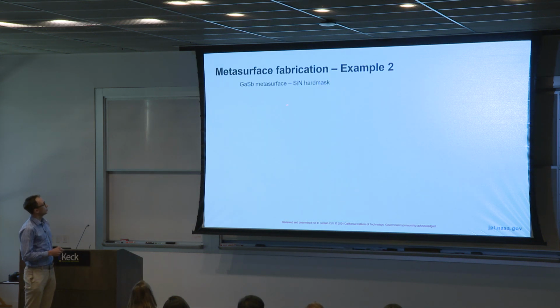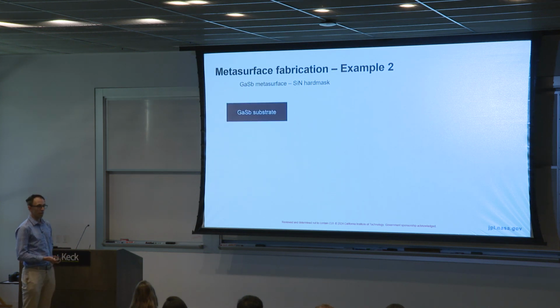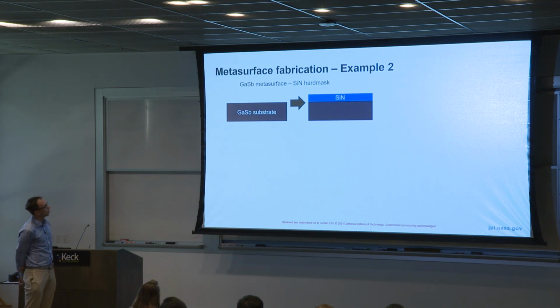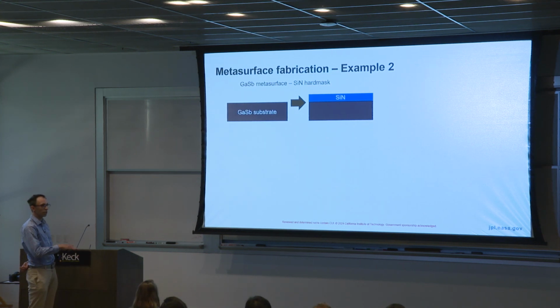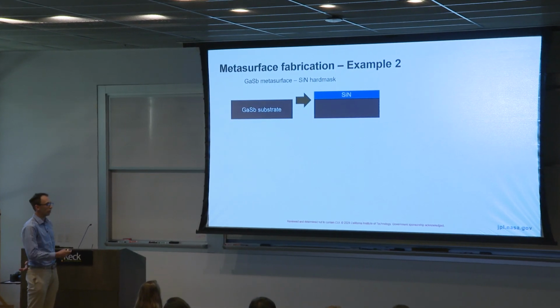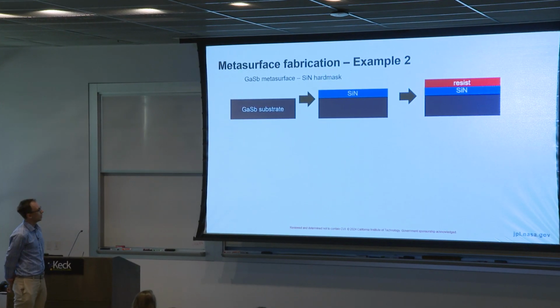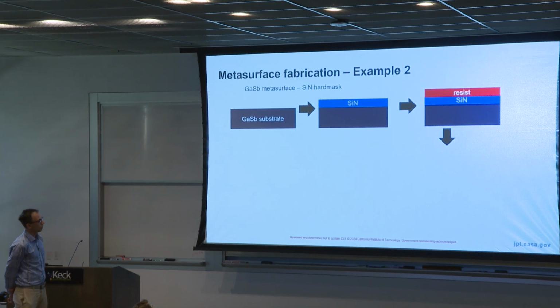In this case, I'm going to utilize a silicon nitride hard mask. That's a pretty hard material, so it's not a photoresist. And I'm going to etch into gallium antimonide, which is a completely different material from silicon, obviously. So you would start with your gallium antimonide substrate. You would deposit silicon nitride using your favorite method. Here you're doing a blanket deposition, so it doesn't matter too much exactly what your method is, as long as you're getting good material quality, as long as it's hard. And then on top of that, you would spin coat your photoresist or E-beam resist.